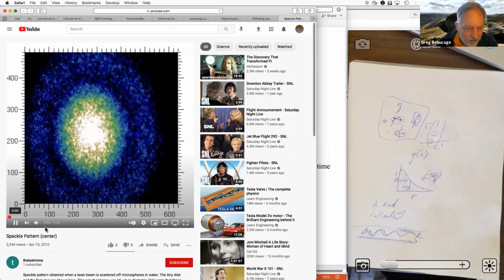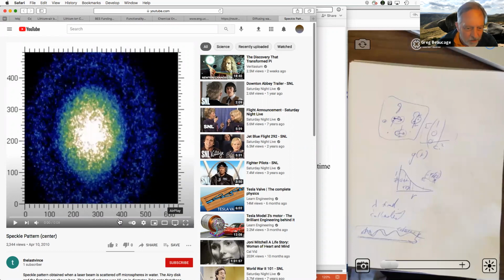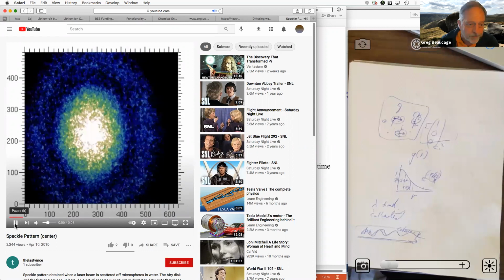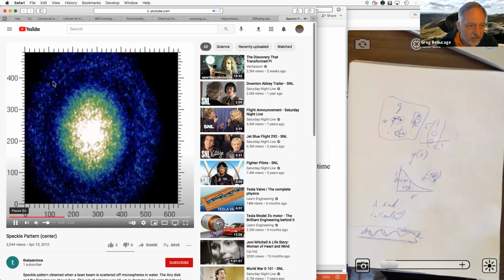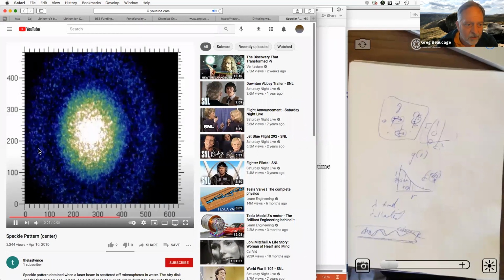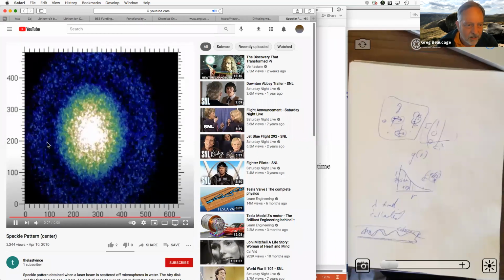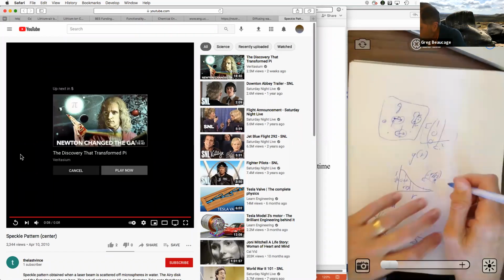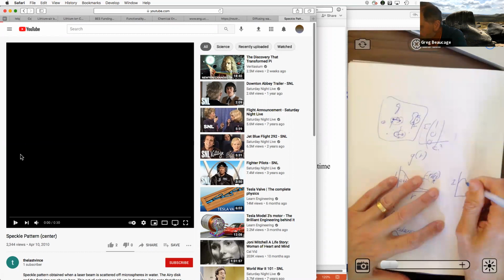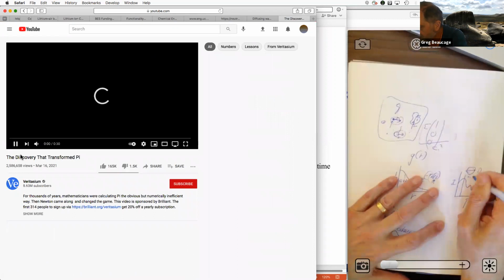I wonder if I can get this to repeat somewhere here. It's probably a button that does that, but so it's flickering. You can see there's a size scale. There's a ring here associated with the size scale of the particles. These are spherical particles, and the scattering pattern. You look at intensity versus Q for a sphere. It's going to have a bunch of peaks that have to do with this fixed perfect size of the sphere, the diameter. And 2 pi over that Q gives you the diameter of the sphere.